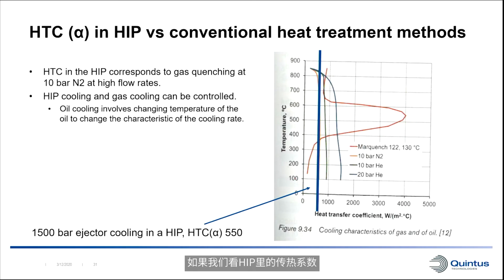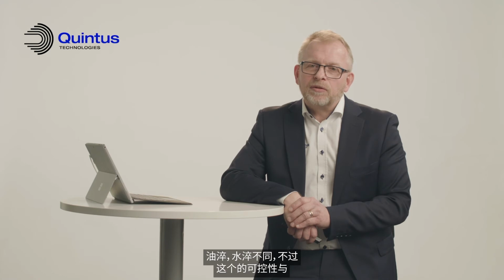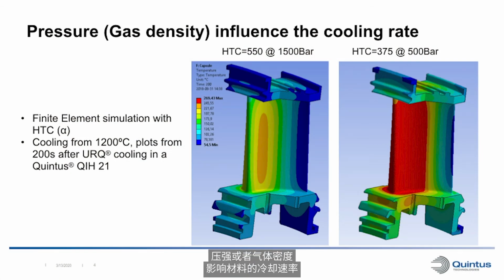If we look at the heat transfer coefficient in a HIP compared with conventional heat treatment methods, it's very similar to a 10 bar nitrogen quenching. It's very different, of course, from oil quenching, water quenching. But what you can say is that the controllability of this is extremely good compared with putting this in an oil bath or something. The pressure or the gas density influences the cooling rate in the material, because we know that the heat transfer coefficient changes with pressure.